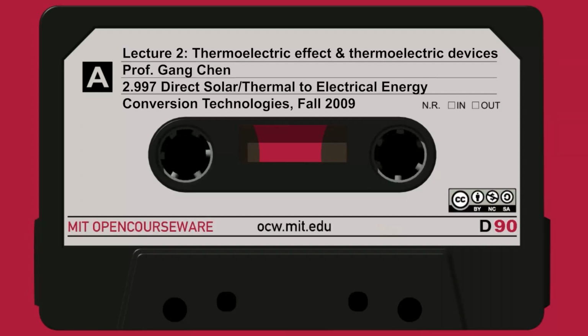So you go to optimize your current, right? That's the arithmetic. You set the derivative equal to 0, and you find the optimum current, and then under optimum current, you got to maximize efficiency, or COP. Of course I dropped all the math. And let me again make a comment. For cooling power, that's easy because there's no denominator here. You got the optimal current for maximum cooling power. Here, you got an optimal current for maximum efficiency, and the two do not agree with each other. And in fact, in your operation, you want to adjust your current just in between. You can't satisfy both. You go optimal current, you don't have much cooling power.